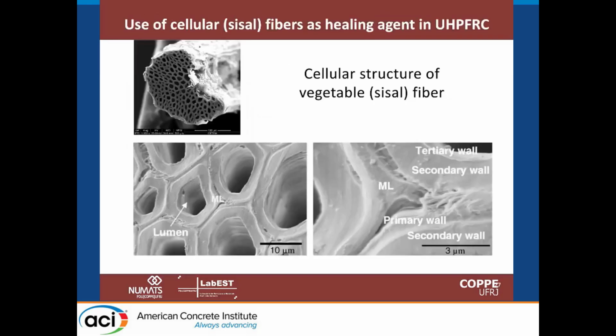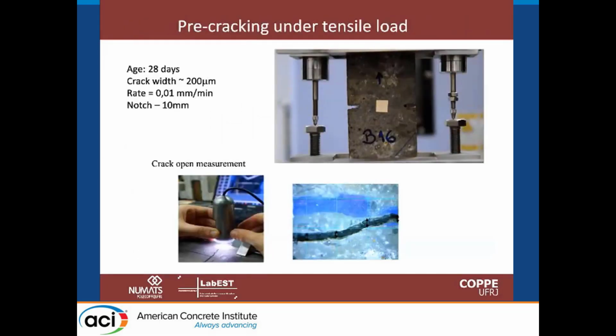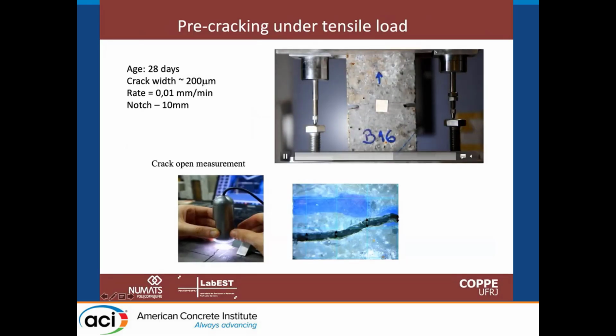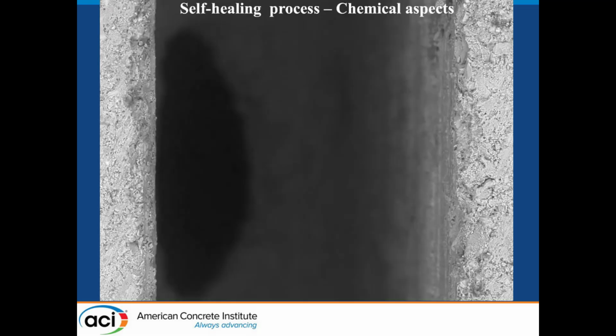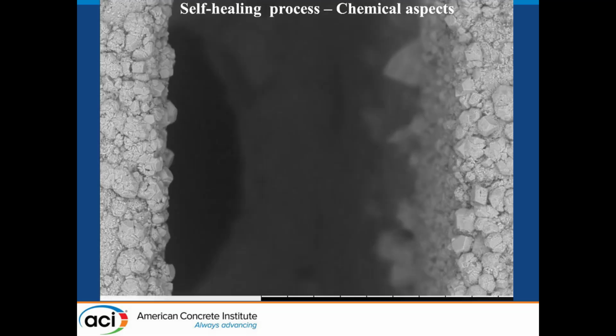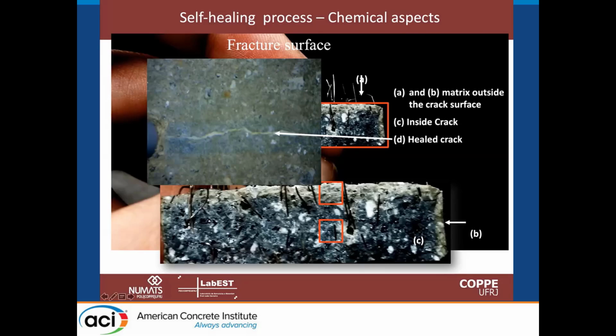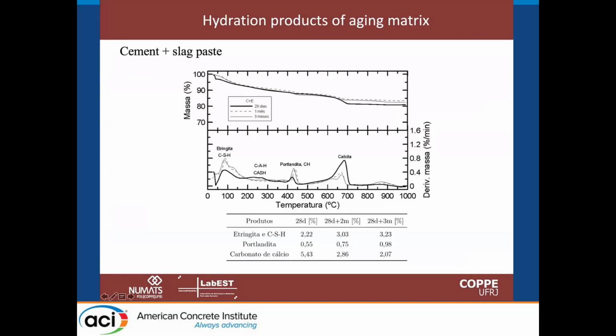The structural cellulose structure of these fibers can also help the healing of microcracks in concrete, and this was done using ultra high performance fiber reinforced concrete. We induced a thin, controlled crack under tension, and later we investigated the phenomenon of healing products growing in this crack. We see here that we could completely heal the crack due to the formation of CSH products, other products, and also calcite. So if we promote the inner porosity that the fibers can bring, it works,